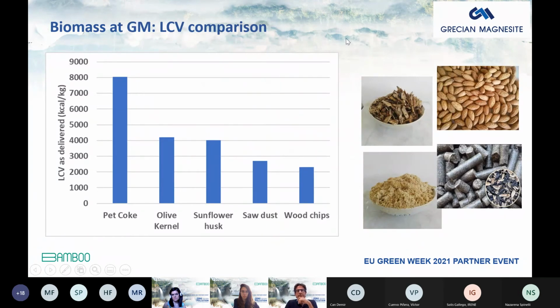If we were to make a rough heating value comparison on an as delivered basis, of course, pet coke is the champion in our comparison here, with almost 8,000 kilocalories per kilogram. And second and closely third are the olive kernel and sunflower husk. Then come the sawdust and wood chips. The reduced sawdust and wood chips heating value observed here is mainly due to the large moisture contents, water contents of these biomasses.